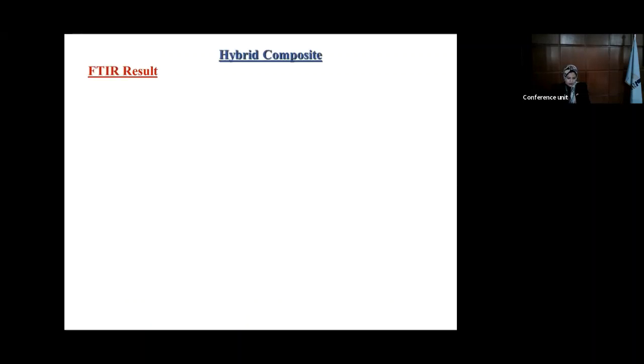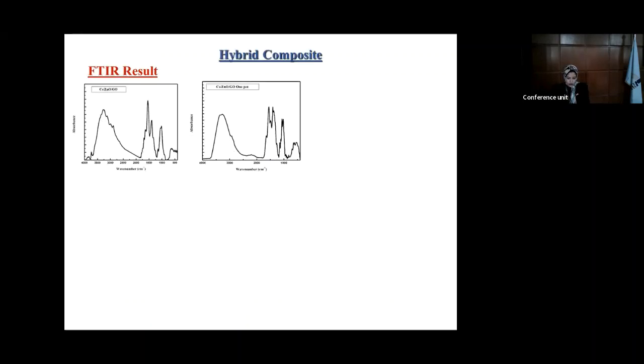For the FTIR spectra of the hybrid composite with the two different preparation methods, both show the typical chitosan bands of the two samples. A new band appeared at 1657 and 1652 cm⁻¹, which is assigned to the carboxyl group from graphene oxide and is downshifted because of hydrogen bonding between the graphene oxide and zinc oxide.